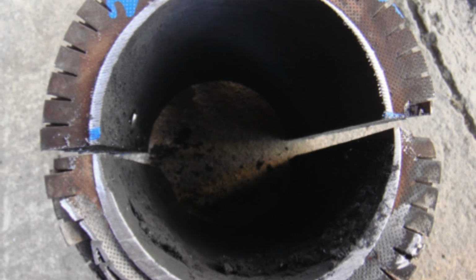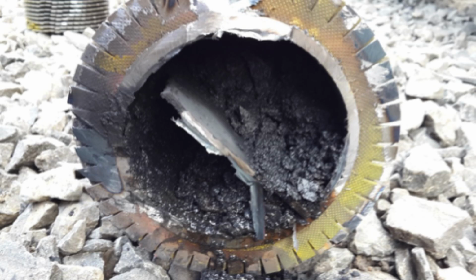You can see all of the damage from the inside, and you can see the top side is very thin and the bottom side is very thick. Yes, but definitely it is from inside, from the water side, and therefore it's the water's fault. But what was quite interesting was the amount of corrosion products that was collected at the low flow area. But in any case, after a long investigation, what we actually did find was that there was insufficient